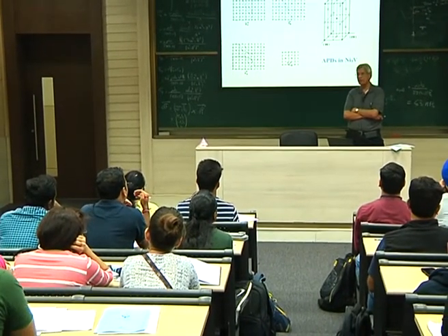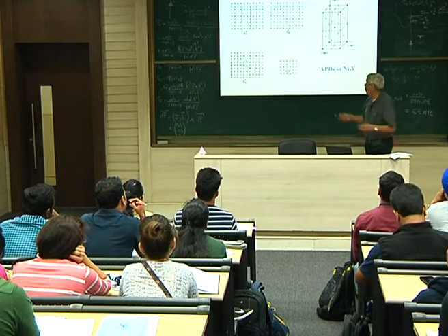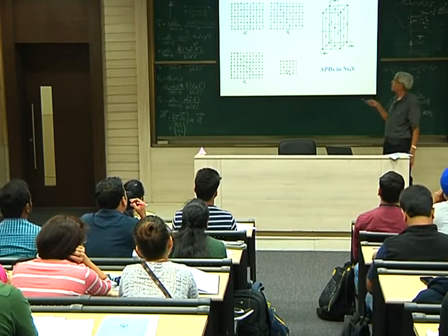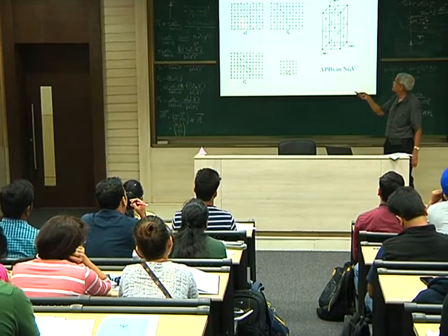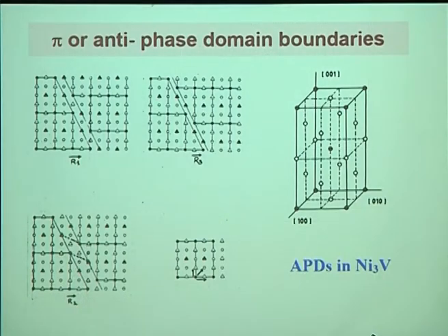Stacking fault also, it's the same, that doesn't matter. So essentially, if you look here, this is an ordered phase, and this is a body-centered tetragonal lattice. The projection of it, if you view it from the 100 direction, is shown here. From here to here the directions remain the same, but if you fix a coordinate system here, you find that the lattice is slightly shifted by a vector. This vector is called the antiphase boundary vector.